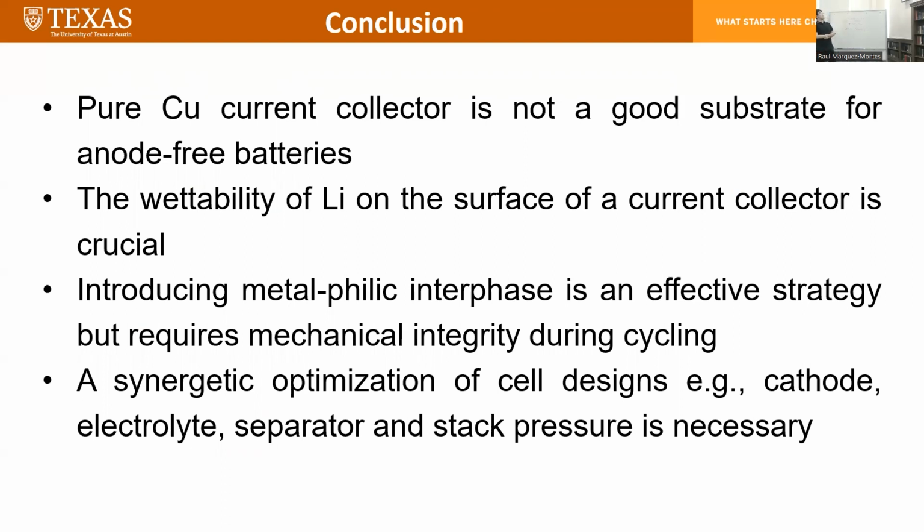The third is that introducing a metal-philic interphase is an effective strategy, for example, alloy materials, but it requires mechanical integrity during cycling. You don't want those materials falling off, because that will lead to early failure of your cell in an anode-free battery. And that's the incentive for us to design those stable intermetallics.